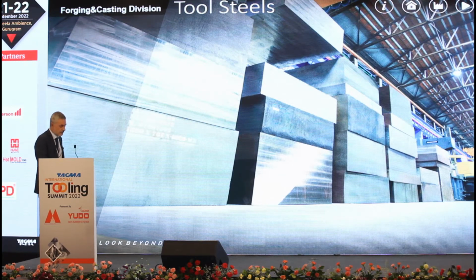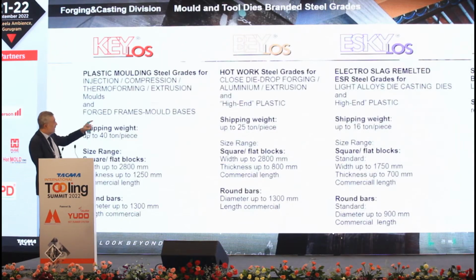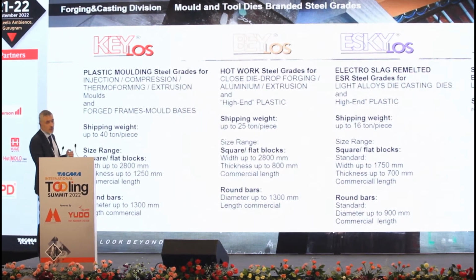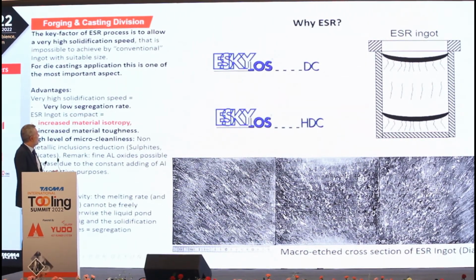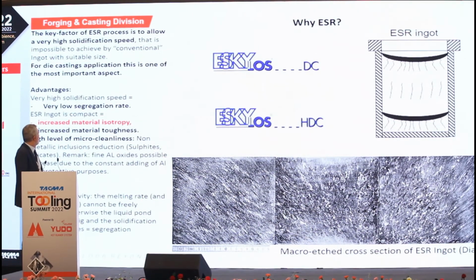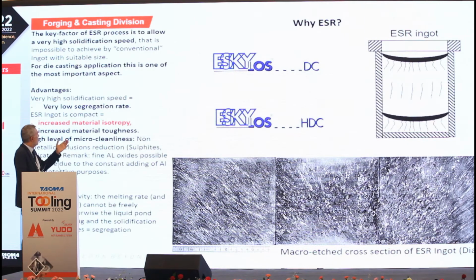concerning tool steels. We have 3 brands. Keylos is the brand for our plastic mold steel grades. Beylos is the brand concerning hot work steel grades and also high-end plastic. And Eskylos is the brand we use. And the key factor of ESR process is to allow a very high solidification speed that is impossible to achieve by conventional ingot. So for die casting application, this is one of the most important aspects.